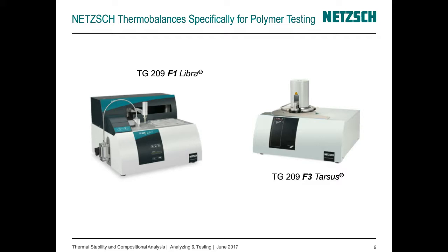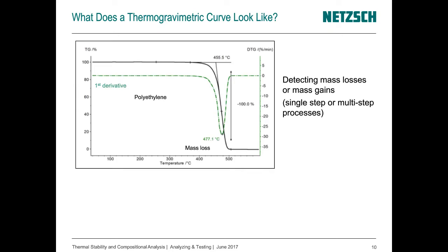But let's first have a closer look at a TGA curve, or TG curve, itself. What we see here is a measurement carried out on polyethylene, and we see in this graphic two curves: a black solid line which represents the mass change, the TG curve, and a green dash-dotted line which represents the first derivative, that means the first derivative of the TG signal versus time. The polyethylene was heated in inert atmosphere, in nitrogen in this case, and we see a complete mass loss of 100%. This mass loss step takes place between, let's say, 400 degrees C and about 520, 530 degrees C.